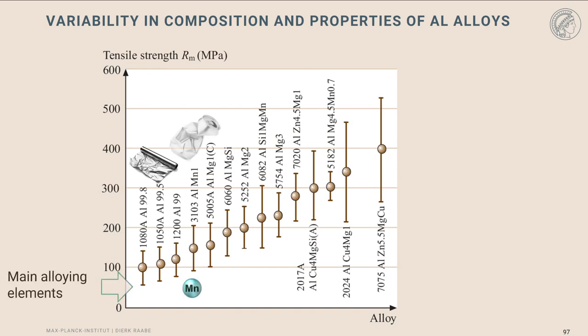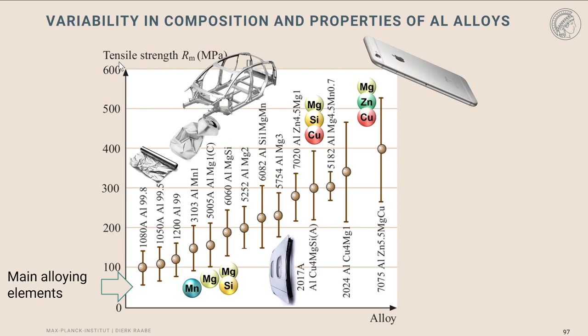This is shown here for the case of aluminium alloys. We plot here the tensile strengths of aluminium alloys as a function of the overall alloying content. And you see here the main aluminium alloy classes like the 1000 alloys, which are relatively pure and used for packaging. We see the manganese containing 3000 series alloys also for packaging. We see the higher strength 5 and 6000 series alloys that you, for instance, encounter in car design. And we see really high strength 7000 alloys that you use for plane components, for cars, but also for mobile